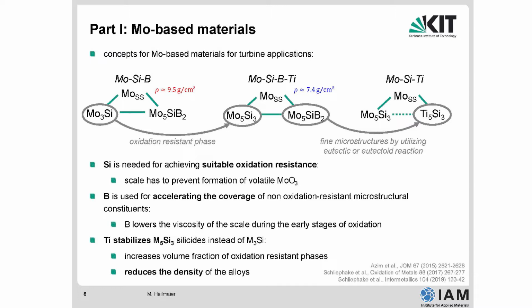Namely, you can still achieve good properties with a simple ternary alloy consisting of molybdenum, silicon, and boron. The titanium, if you don't use the boron, stabilizes a different phase than this one here. This one is an oxidation-resistant phase, and the question was, an unsolved question in science, whether this titanium 5 silicide is good or not in the alloy. If you synthesize a pure Ti5Si3 phase, this would oxidize rapidly at temperatures beyond 1000 degrees. I will show you that this is surprisingly not the case for the alloy of interest here.